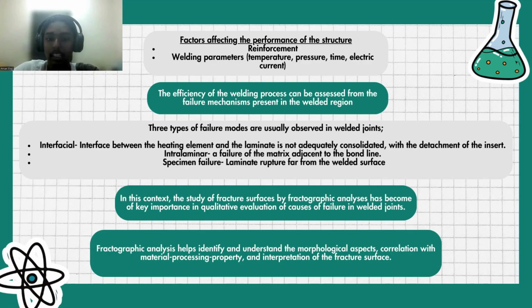Interfacial: the interface between the heating element and the laminate is not adequately consolidated, with the detachment of the insert. Intralaminar: a failure of the matrix adjacent to the bond line. The specimen failure, which is the laminate rupture far from the welded surface.